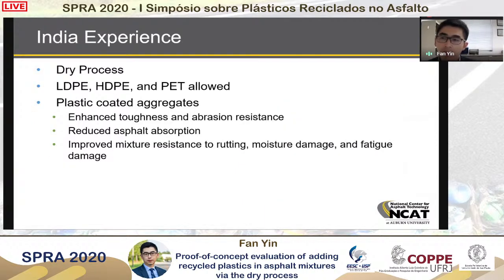I would say probably India is definitely the leading country on using the dry process of adding recycled plastics. Reportedly, they have almost 15 years of experience with this process. Right now, they have been using LDPE, HDPE, and PET in this type of application. The concept they are going after with the dry process is what they consider plastic-coated aggregates. What that means is we're adding recycled plastic into the hot aggregates. Because of the high temperature, the plastic is going to melt and coat the surface of the aggregate.